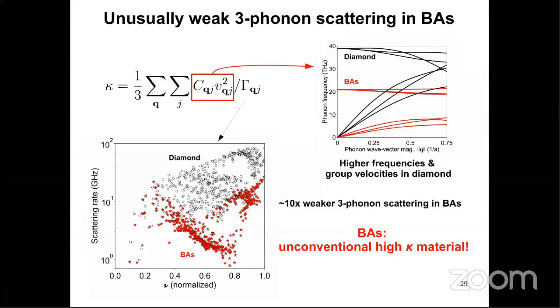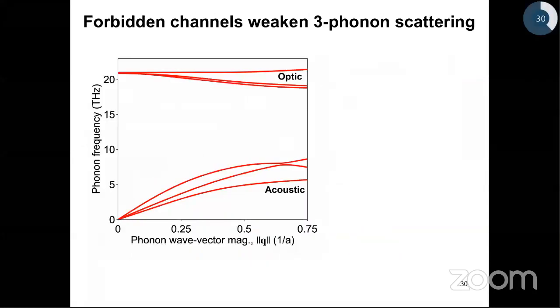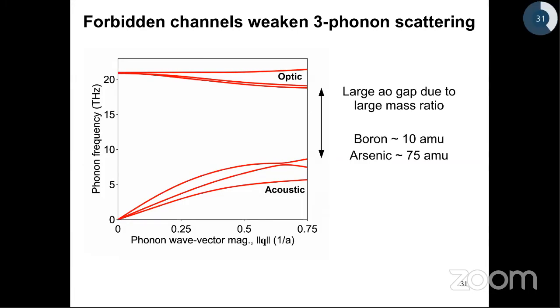So this shows that boron arsenide is achieving this high thermal conductivity in an unconventional manner, that is defying the conventional guidelines. So what causes this unusual weak three-phonon scattering rates in boron arsenide? Let's go back and think about it from the dispersion perspective. So here I am showing the phonon dispersions for boron arsenide. You have 3 acoustic and 3 optic branches. And because boron arsenide has a large mass ratio between boron and arsenic, you have a large gap in frequency separating the acoustic and the optic phonons.